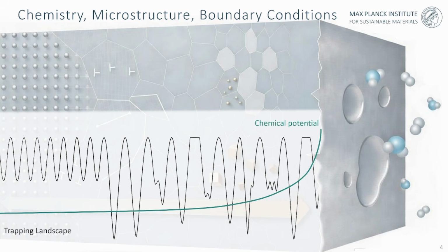Very often you also encounter gradients in the chemical potential of the hydrogen. That means you do not have any homogeneous hydrogen embrittlement in the material, but the profile of the chemical potential of the hydrogen can change, for instance, from the surface to the center of the material. That means you can even have scenarios where the hydrogen embrittlement effect at the surface differs from the hydrogen embrittlement effects deep inside of the material. So all these aspects must be taken into consideration, whether you, for instance, have to passivate the material, change the interfaces, use certain chemical variants, or whether you protect the materials by using coatings, for instance.